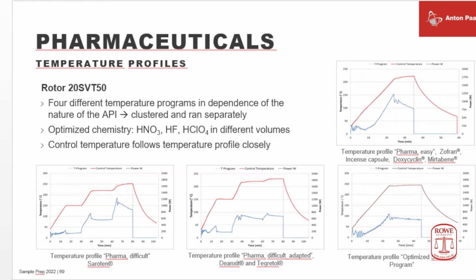For instance, if you have titanium dioxide as a filler, very commonly used in pharmaceutical substances, you need the HF to dissolve the titanium dioxide. And to increase the oxidation potential, also perchloric acid is used in small amounts. The exact amount you can read from our application reports. Perchloric acid is used to increase the oxidation potential in cases of very hard to destroy sample materials.